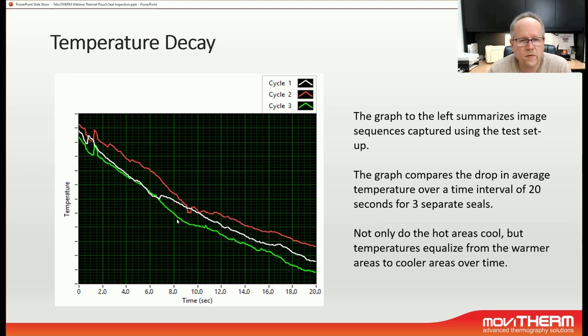And you can see that the temperature overall is decreasing over the period of 20 seconds, which we have monitored. And if you remember from a couple of slides before, at about 8 seconds, everything was completely blurred out, and you can see the decay slowing down and becoming a little bit more noisy, which means that the temperature energy has dissipated to a level where it has equalized, and therefore we can't see anything anymore, and it has become very blurry. Another interesting thing to see here is that right after the beginning of the cycle, we can see a little increase in temperature, and that is most likely due to something deeper in the material, such as the adhesive that has been heated, and the heat is still rising to the surface, and then it's cooling down further here. So this is an interesting test that also helps us analyze what's going on based on the material thicknesses and the thermophysical properties involved and everything else we need to know.